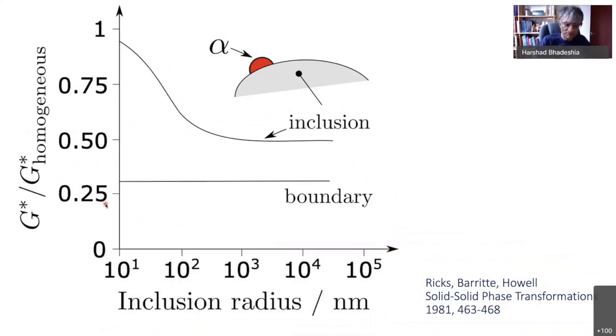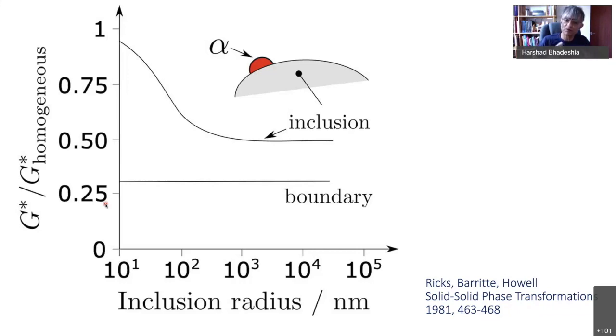Sometimes when we get ferrite grains forming inside an austenite grain, it's actually advantageous from the point of view of fracture, because you will get grains in many different crystallographic orientations, and therefore the cleavage crack path is deflected frequently through the material. So you get an improvement in toughness, and that's really important because when we make strong materials in general, the toughness will decrease.